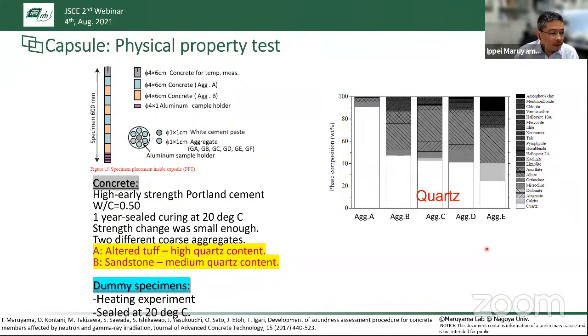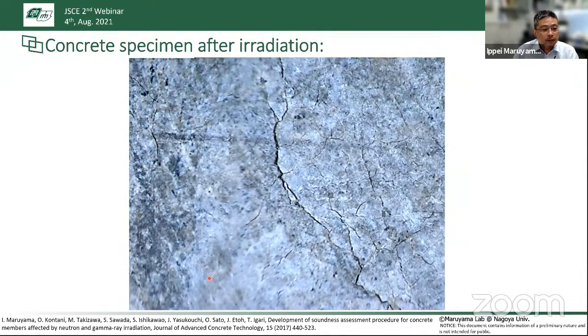And we also prepared the dummy specimen. We made the dummy specimen to get the data after the heating experiment. As I mentioned, during the neutron irradiation, we will see the temperature increase in a specimen. Therefore, to separate the impact of the neutron with respect to the temperature, we also did the heating experiment. So I would like to introduce the experimental results.